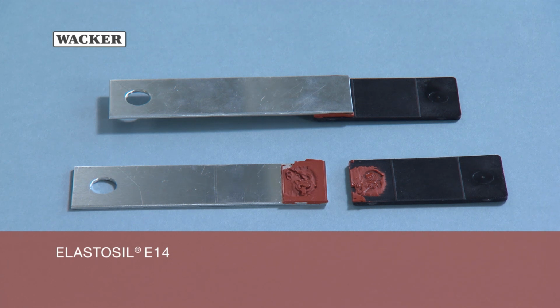ELASTOSIL E14 primarily exhibits cohesive failure on aluminium and polyamide. Depending on the substrate, adhesion properties of silicone grades may vary considerably and must be tested on a case-by-case basis.